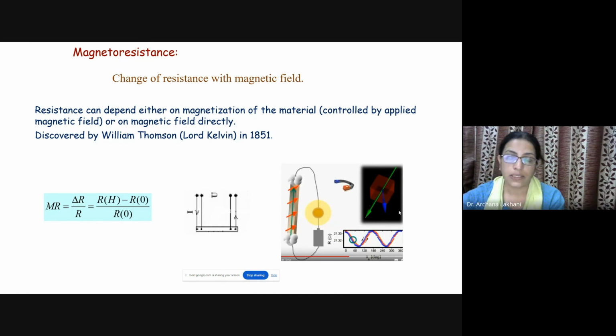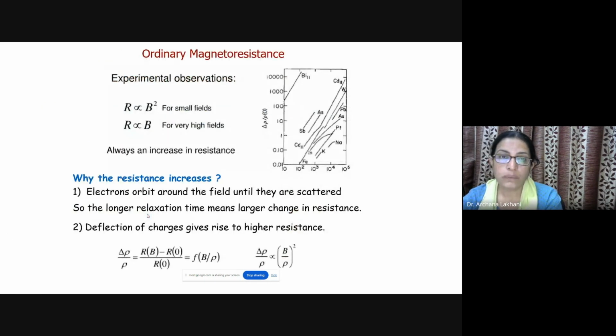So what is magnetoresistance? When we combine resistance with magnetic field, when we measure the change of resistance with magnetic field, that is called magnetoresistance. And this resistance can depend either on the magnetization of the material as well as on the external magnetic field applied. So magnetoresistance is given by the change in resistance with field as well as without field, and this ratio provides us the magnetoresistance. If we multiply by 100, we call it magnetoresistance percentage, which we usually talk about in our measurements. The experimental observation for ordinary magnetoresistance is that resistance changes quadratically for small fields but linearly at high fields.